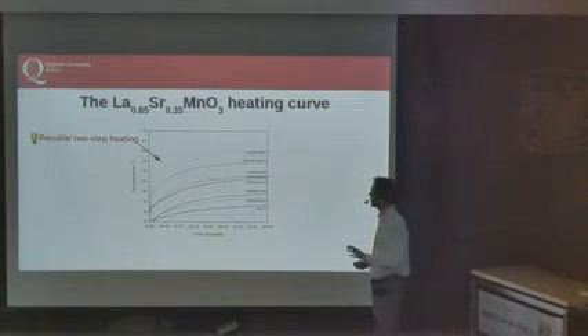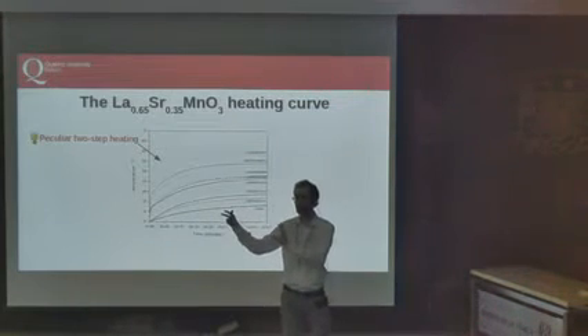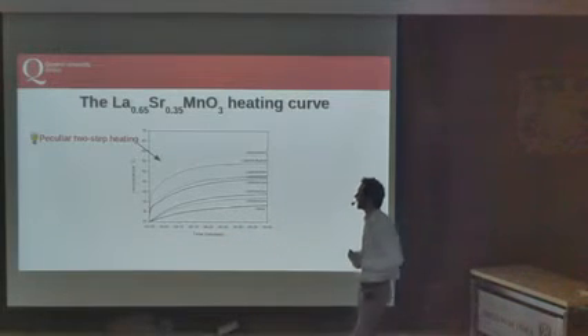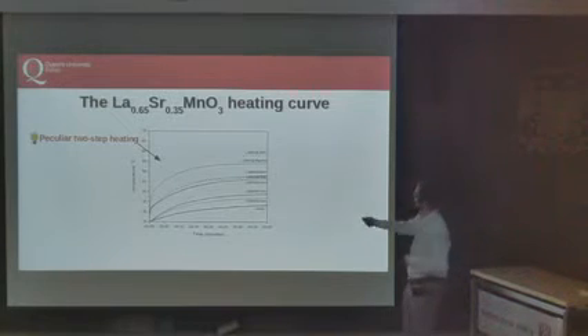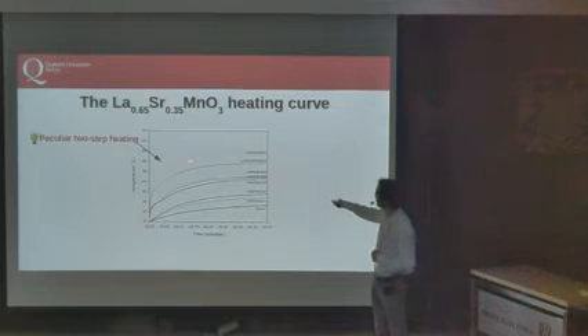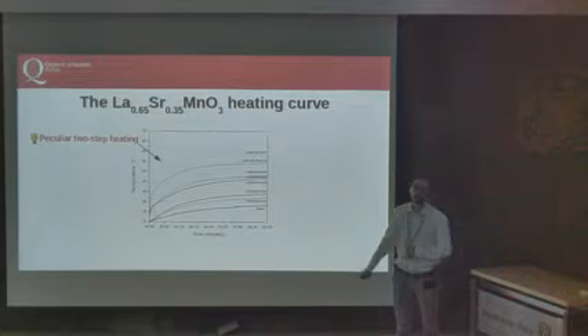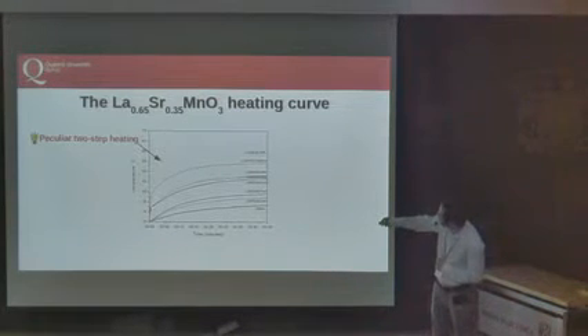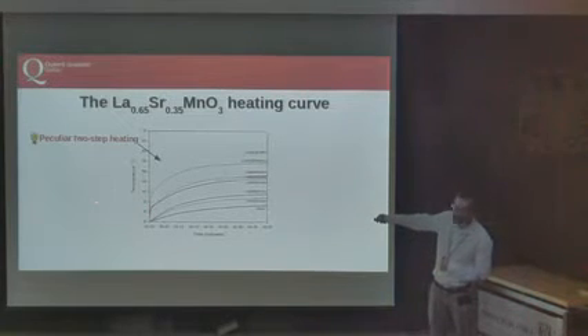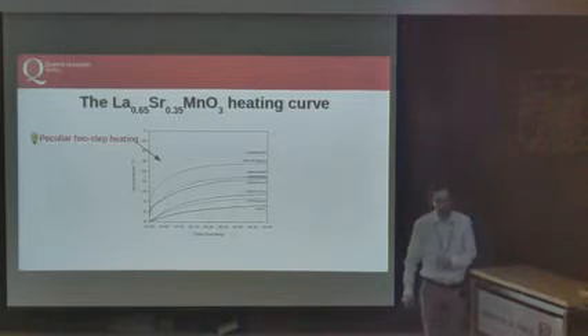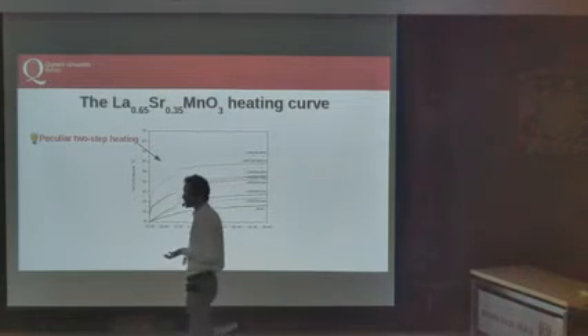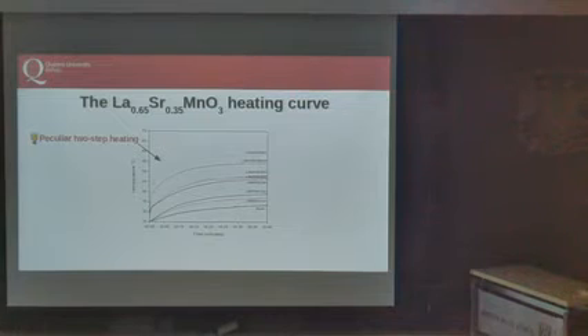But first of all, we have to characterize in more detail the heating curves so that we can match the macroscopic values that we get from the experiments to the microscopic values that we get from the simulations. In particular, if you look at the highest curve, which is again LSMO 35 with microwaves, you see there is a very steep initial rise of the temperature and then something more gentle and saturation. What is this saturation due to? Well, the system is measured in so-called non-adiabatic conditions, so the vial is open, the vial is not isolated, so the heat eventually escapes to the environment. And so there is a balance between the heat provided by the magnetic mechanism and the heat lost to the environment. And this is why we have this saturation.